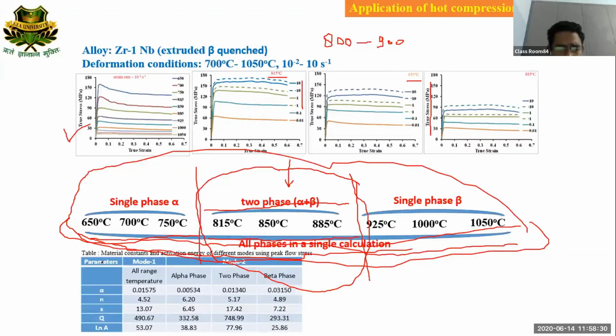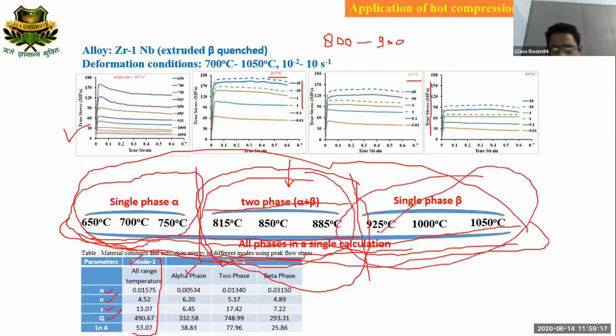Here I am giving the values of the parameters which I have calculated for the development of the constitutive equation: alpha, n, s, q, ln A. Mode 1 is the parameter set developed from the data without bothering about the phases. That means all deformation temperatures are taken in a single range and termed mode 1. In mode 2, I have individually developed the parameters for alpha phase, for the two-phase region, and for beta phase.